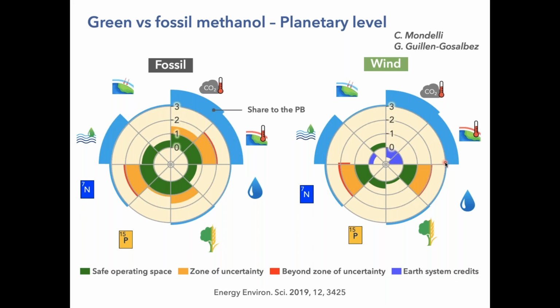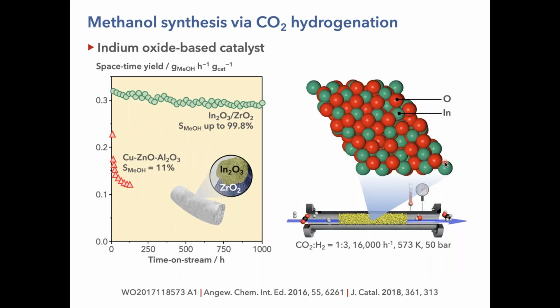look into alternatives. So our work on CO2 hydrogenation to methanol started with the discovery of indium oxide as catalyst for this reaction. And this catalyst is very special because it's highly selective to methanol, so it produces very little CO, as well as very stable. So this is a test over 1,000 hours on stream.